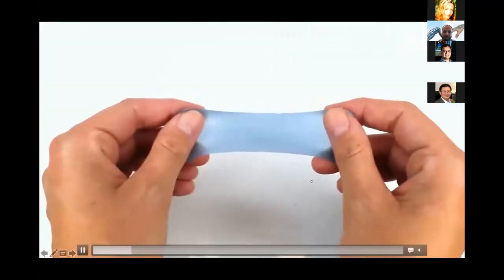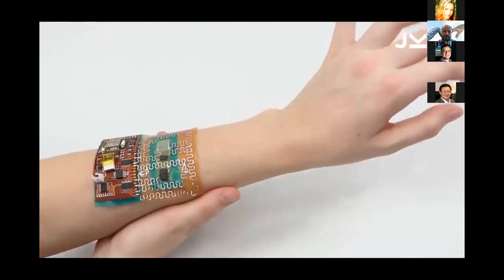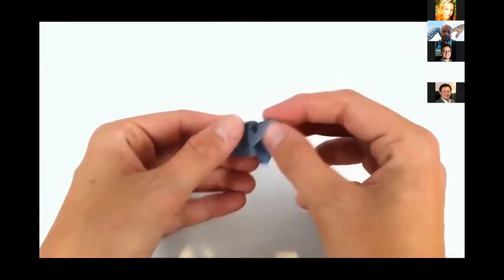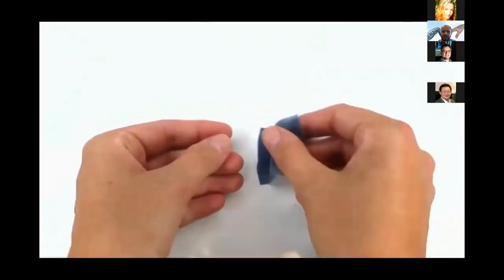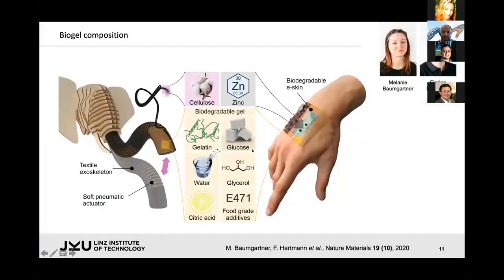So we set out to develop an elastic material that is both extremely stretchable, extremely durable, self-adherent, but entirely biodegradable. It is made entirely from bio-derived, gelatin-based polymers in this case. It is tuned in such a way that it can achieve the performance that we were looking for. So we were working on two ends, so to say. We would like to have these electronic patches made from a soft, stretchable, and degradable material, but at the same time, they should be functional in soft robotic embodiments that usually tend to be stretched to at least 200% or even higher.